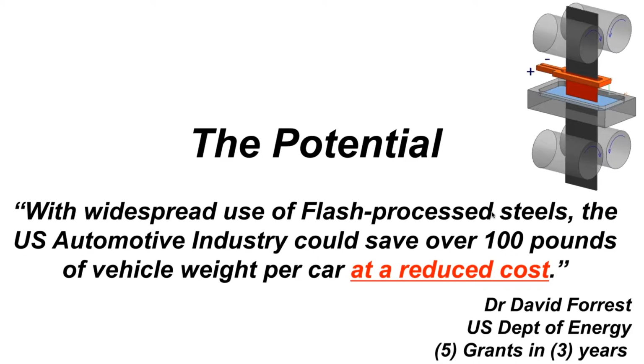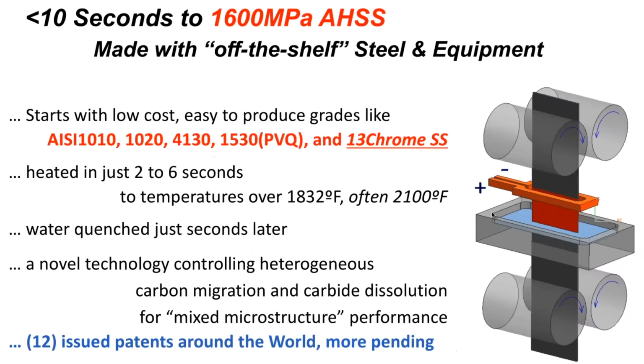So what are we doing here? It's flash processing. Well, the simplest way is to show a picture. So if you look on the right-hand side, we've got a caricature of our process. We feed steel in from the top of this display unit here. We roll past a couple of pinch rolls. We use induction heating to rapidly heat the steel, and we water quench. So we're actually making 1,600 megapascal advanced high-strength steels.